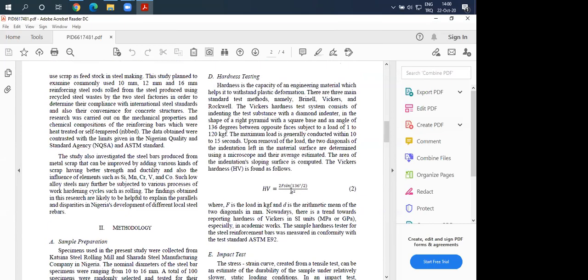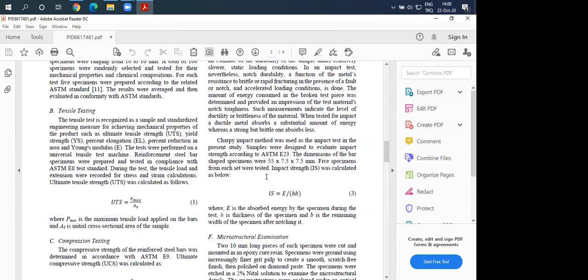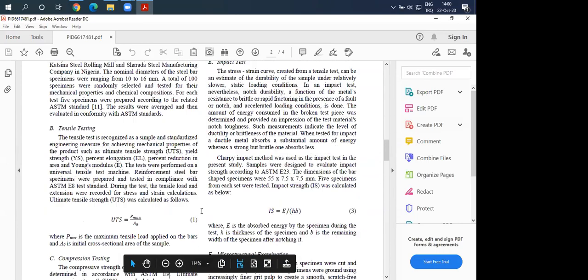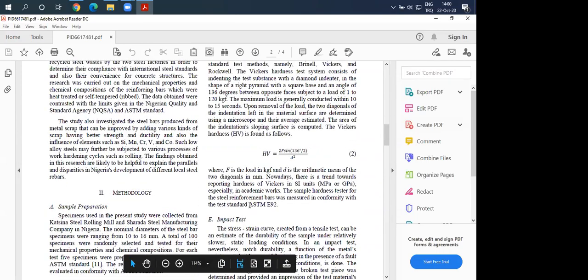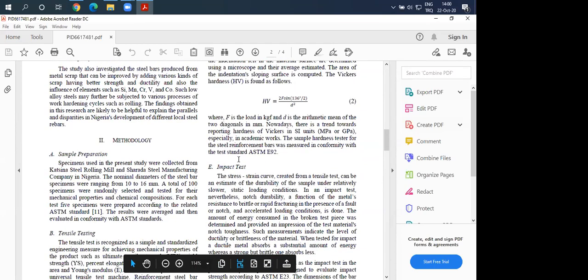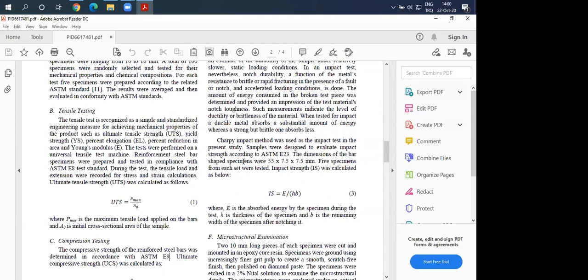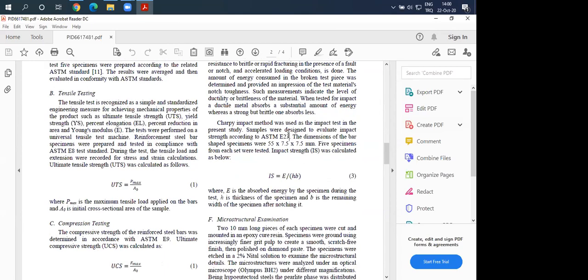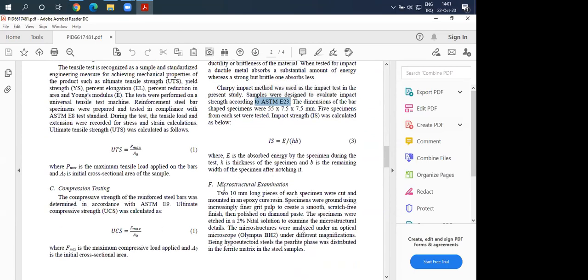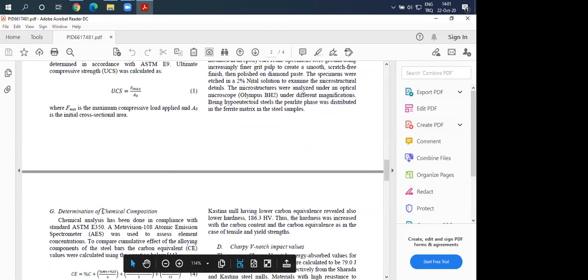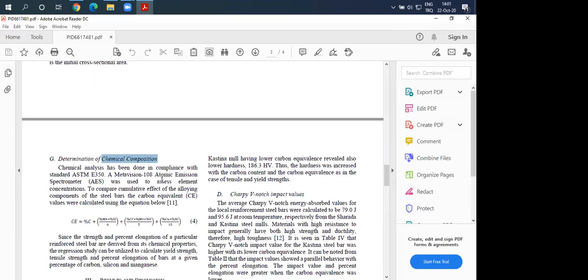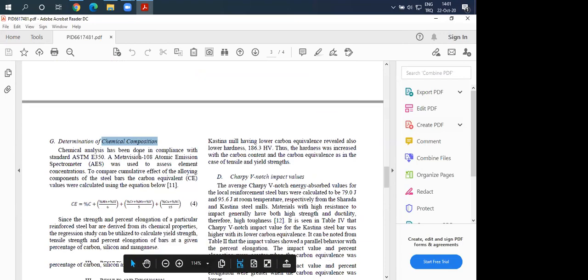And then we have the hardness test, where ASTM E92 is used, and the impact test, where ASTM E23 is used with notched specimens. Microstructural examinations and chemical composition analyses are also conducted. And from these chemical compositions, the CE, carbon equivalent value, was calculated.